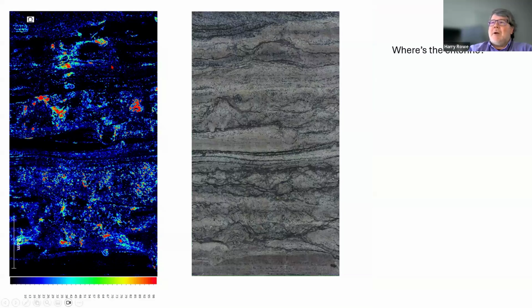This is a micro XRF technique that I've used just to demonstrate that the chlorine content is highly variable across the face. This is just a couple of inches across here. And what you see is that it's just in little pockets. The red is the high chlorine. This is just on a scale from 0 to 100%. So, you know, cleaning this can be very, very difficult. And it generally occurs where there's the highest porosity in the rock.